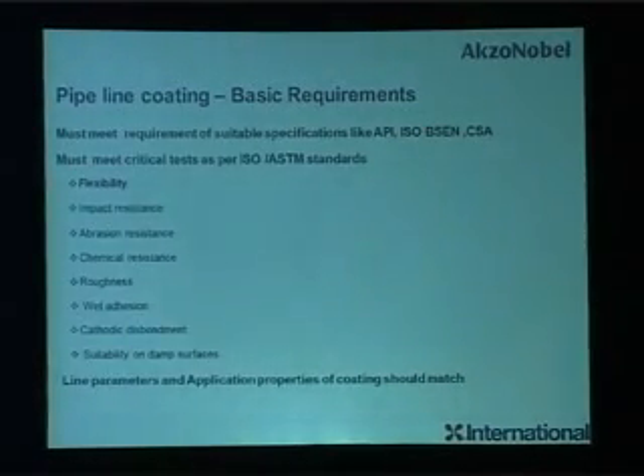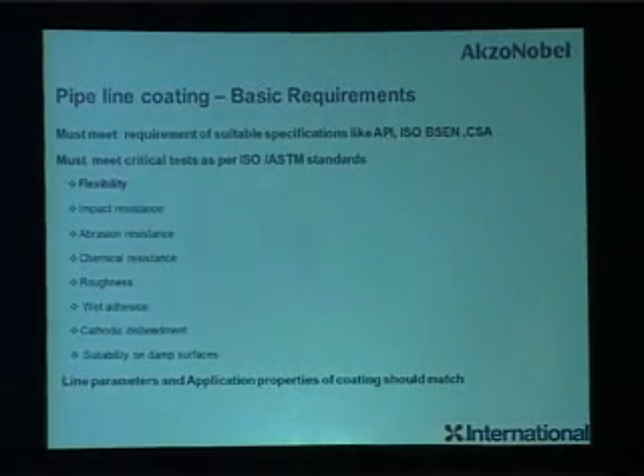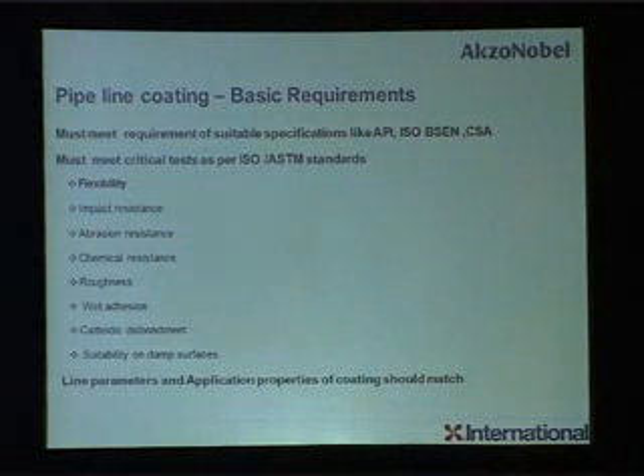One is definitely flexibility. When you are handling pipelines, when you are doing a lot of bending and all these jobs, the flexibility of the coating is very, very important. If it is not flexible, then it can crack. Impact resistance, because when you are taking coated pipe from one point to another, there will be chances of impact, so your coating should bear that impact. Abrasion resistance, definitely chemical resistance, because if you are using internal pipe coating and the chemical going through that pipeline is not resisted, then there will be a problem.